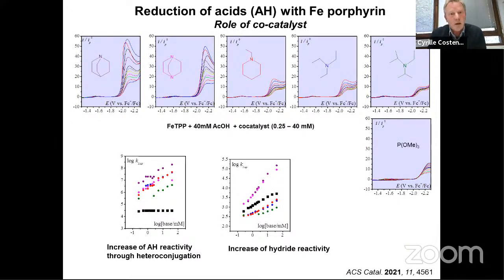To finish on this reduction of acid using iron porphyrin, there is another interesting observation that we did observe: if you add a base in the medium, you get something which is very surprising, which is the increase of the catalytic process. As you can see here, as you increase the concentration of base, you get more and more catalysis, which is kind of surprising because your substrate is an acid, you put a base and you get a more efficient process, okay? And so, as I mentioned previously, in those situations, you can measure the two rate constants, formation of the hydride and reactivity of the hydride, and both are changing as you change the concentration of the base.